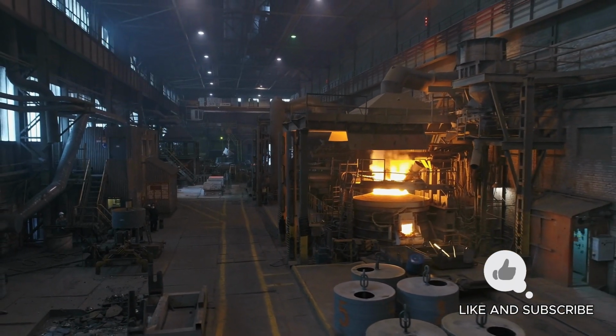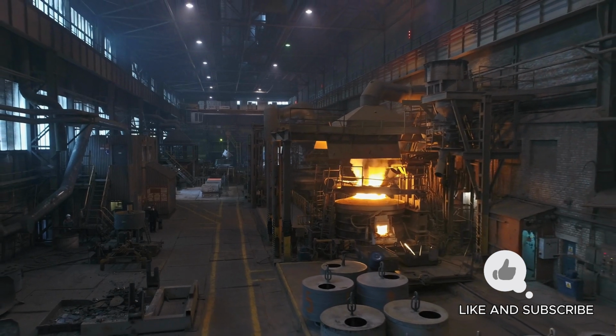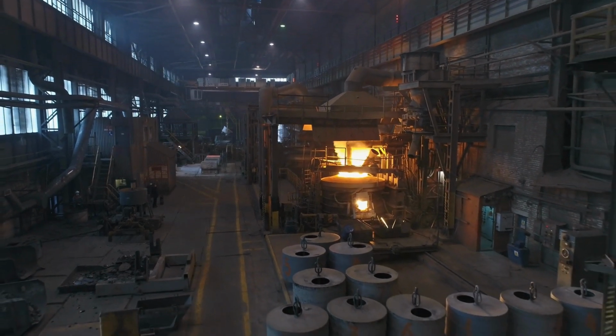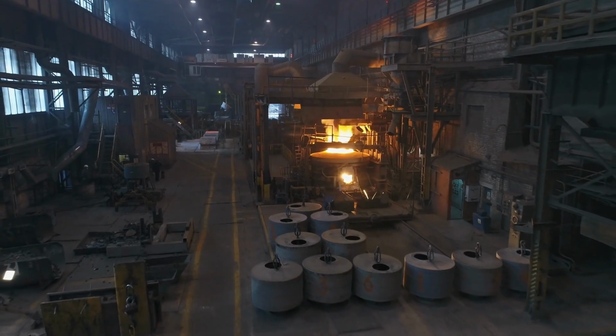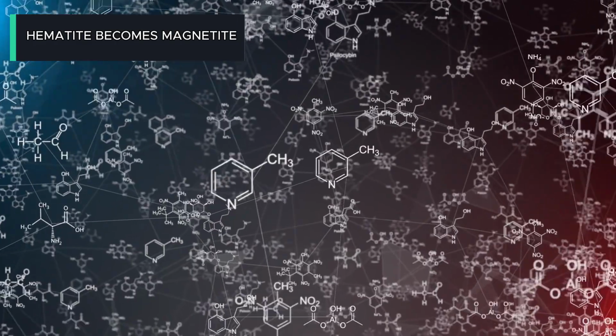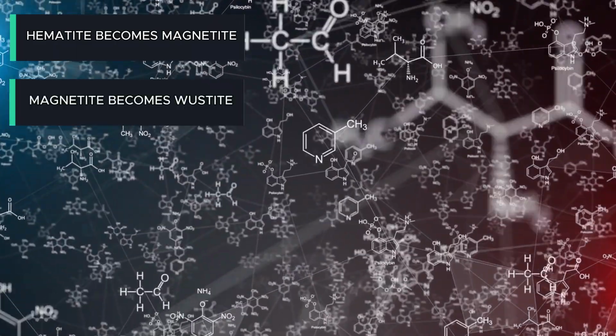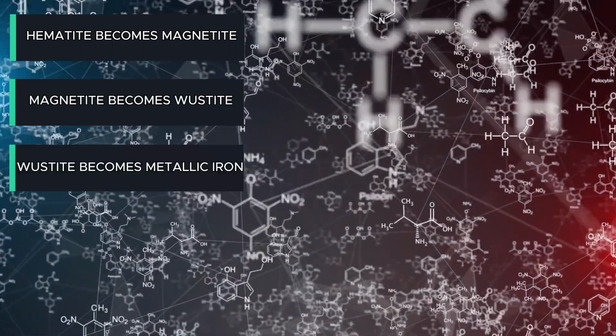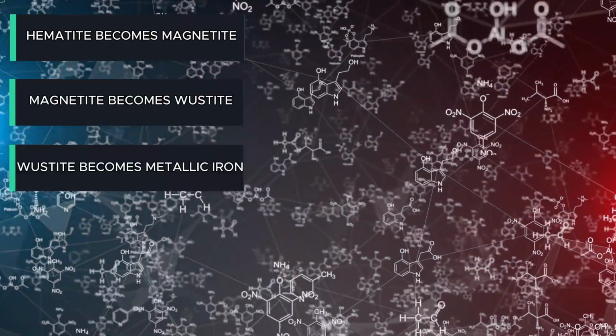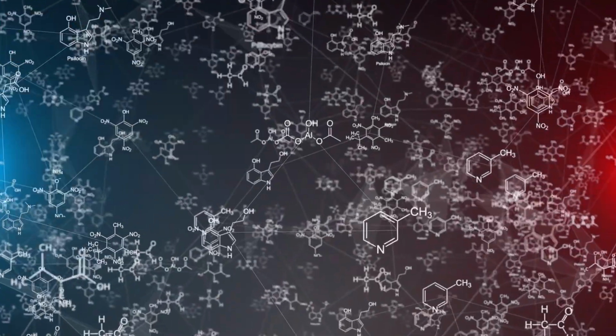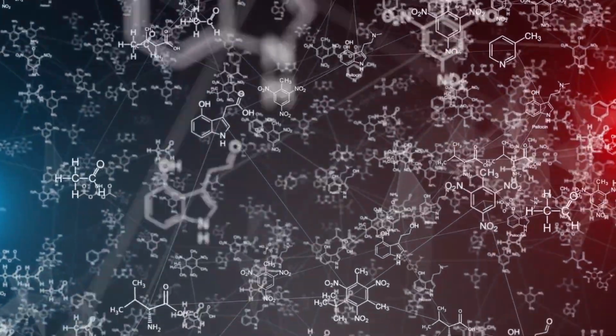Carbon monoxide is the real chemical agent of this entire process. As it rises through the descending ore, it strips oxygen in stages. Hematite becomes magnetite. Magnetite becomes wustite. Wustite loses its final oxygen atom and becomes metallic iron. Freed from the ore, it has been locked inside for millions of years.